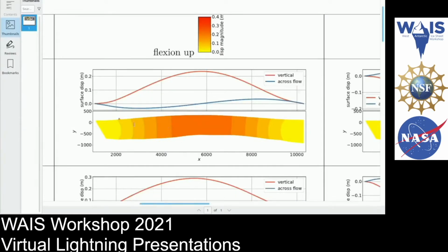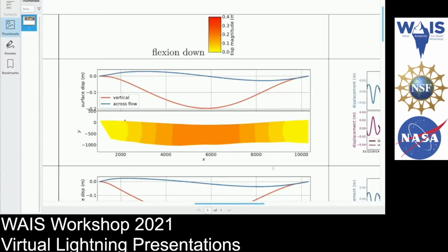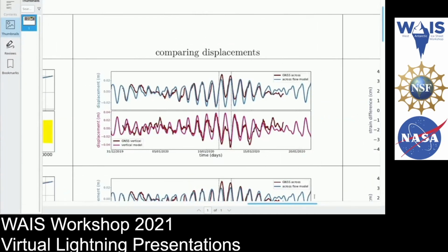So under these conditions, the vertical surface deformation is this red line, and the across flow displacement is this blue line here. And you can see the magnitude of the displacement in these plots here. This is for the negative tide. And then in these plots, we're comparing the GNSS measurements with the outputs of this same model run in a dynamic fashion, so forced using a tidal model.